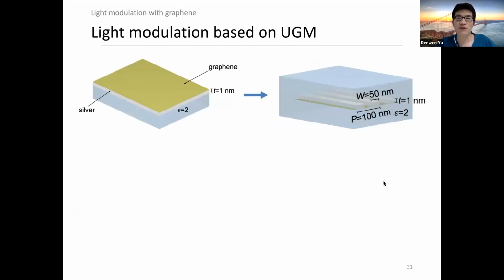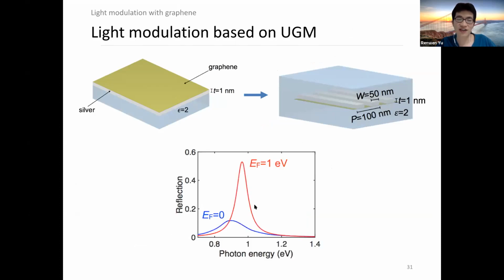And then in order to excite those plasmonic modes supported by this hybrid structure, we can pattern the extended silver films into a periodic array of silver ribbons. And when we look at the reflection, we can see that when we change the doping level of graphene from its undoped state to doped state, we can have more than 40% light modulation in reflection at a photon energy around 0.9 eV.